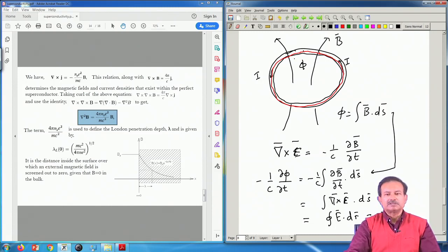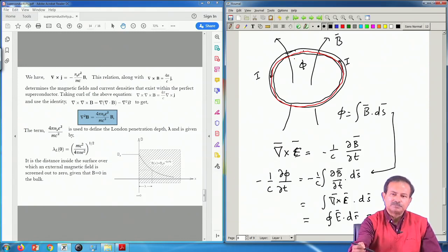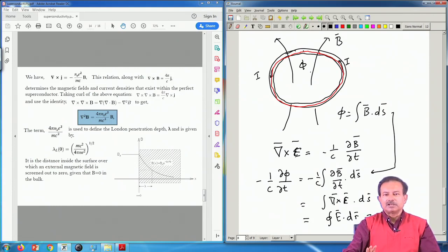And that is what I mentioned earlier in the lecture, that one of the ways to see that you are in a superconducting state is to see that there is a supercurrent. So, how do you know there is a supercurrent? You can actually measure the flux and see that the flux is not decaying. So, one can actually do this experiment, and one finds that this flux is not only constant, it is constant over an enormously long time.